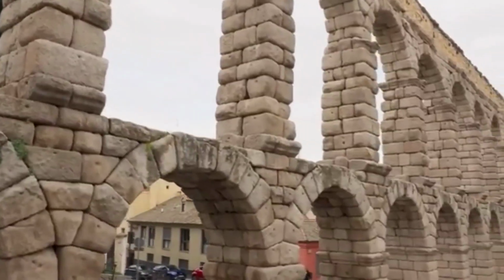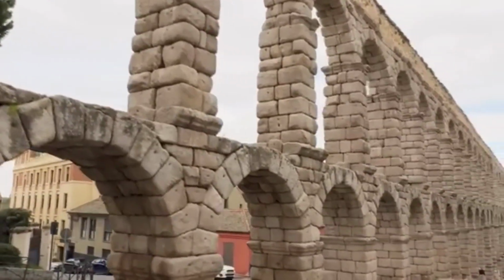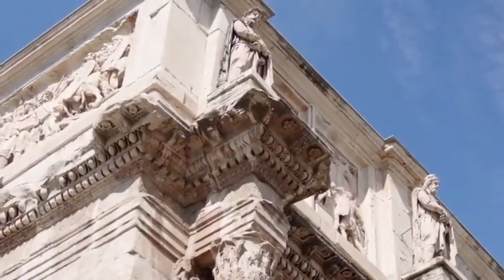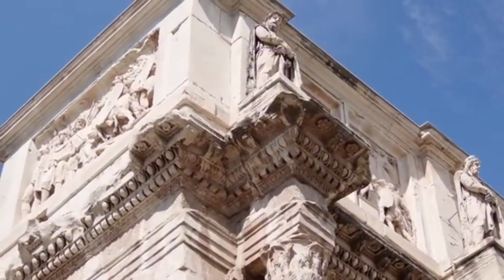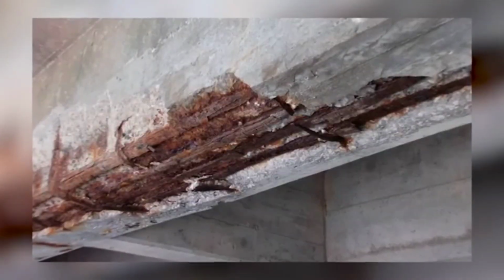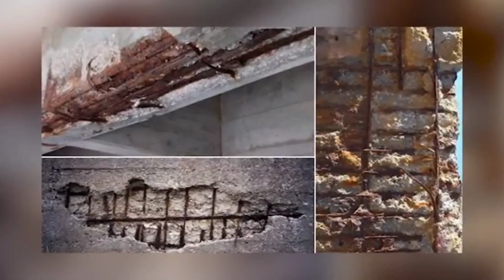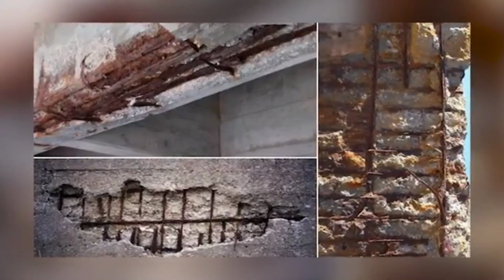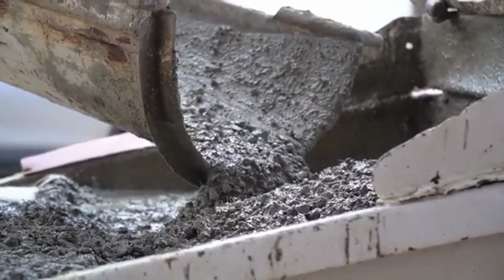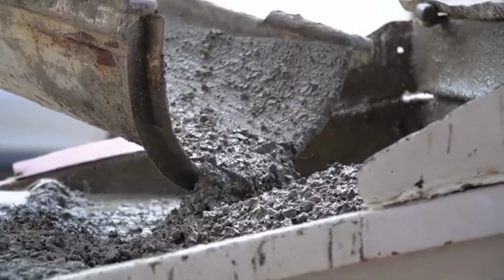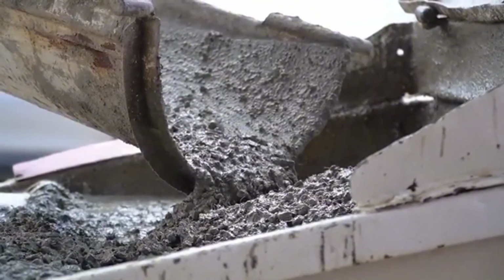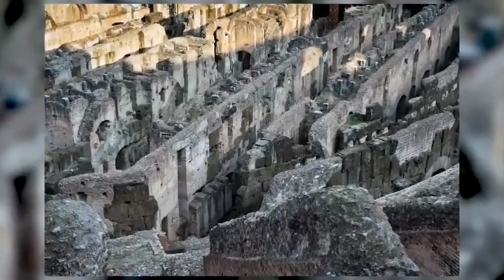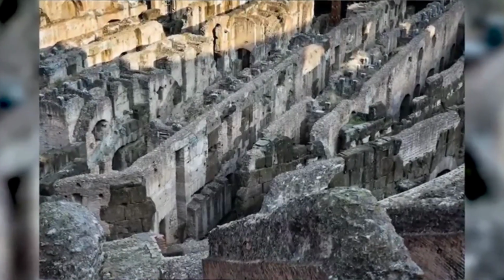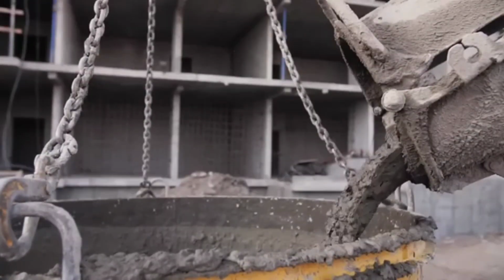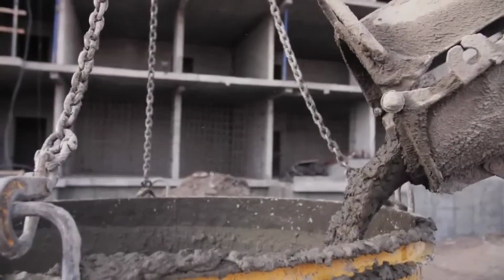The seawater reacted with the volcanic ash and lime to grow tobermorite and phillipsite crystals directly inside the pore spaces and microcracks, filling them, reinforcing them, making the structure denser over time. Modern concrete exposed to seawater forms ettringite crystals, which are 2.5 times the size of their precursors. They expand, they crack the concrete from within. Roman concrete thrived on the same exposure that destroys ours.